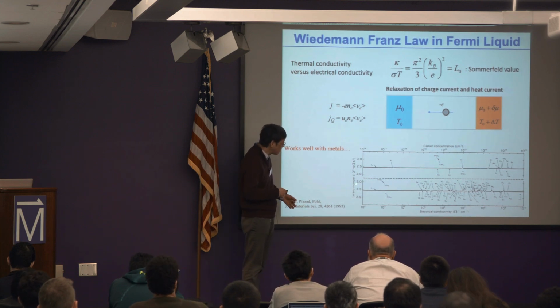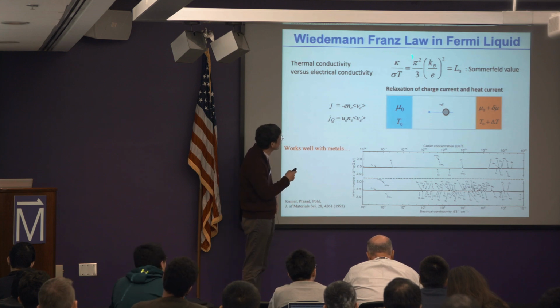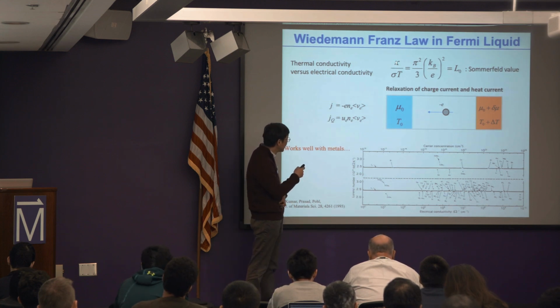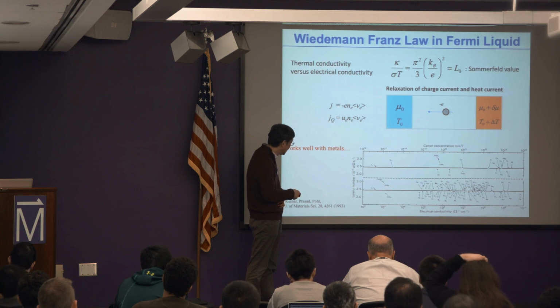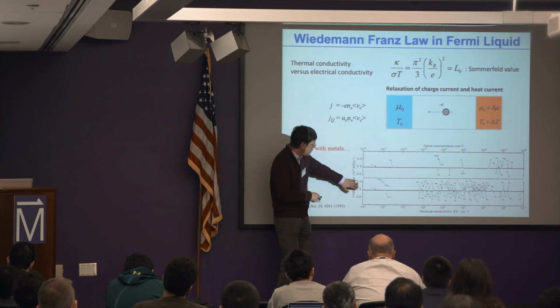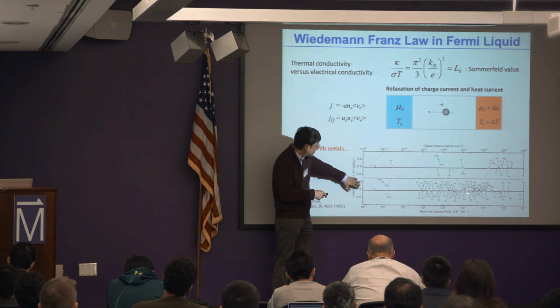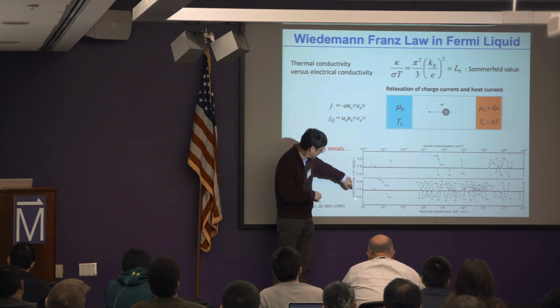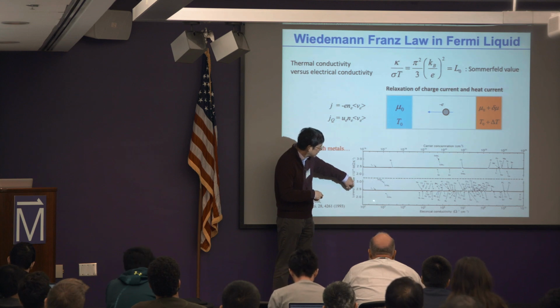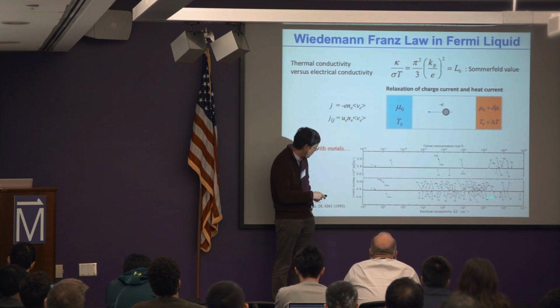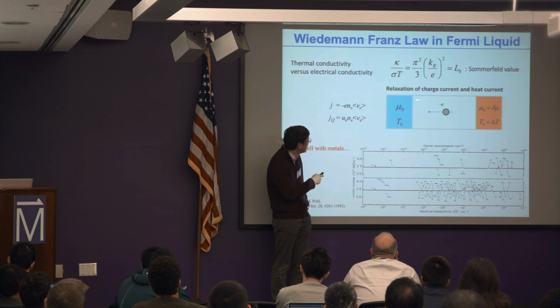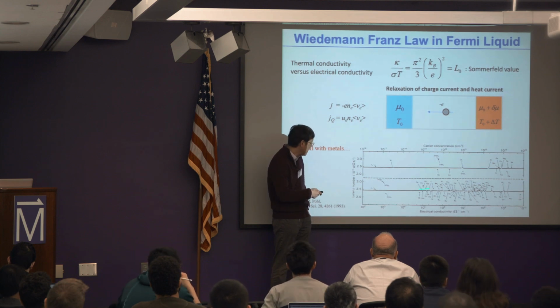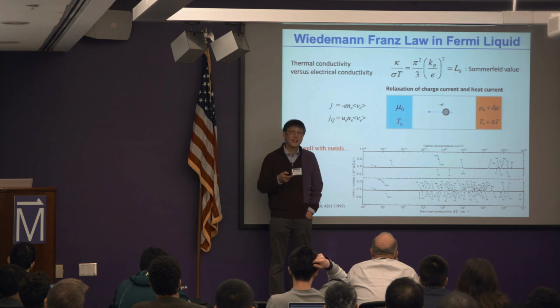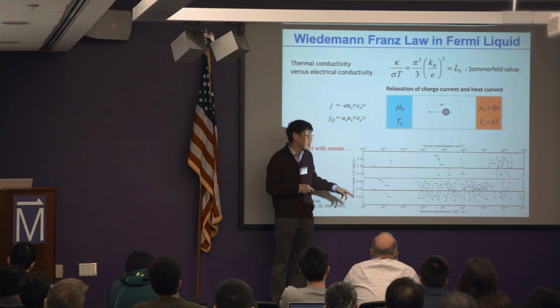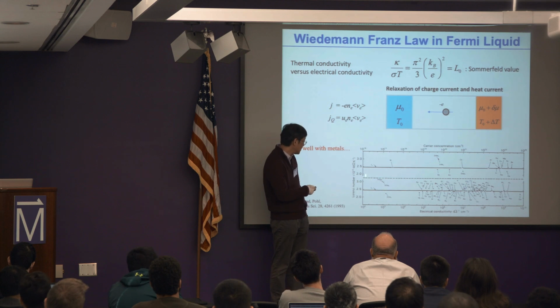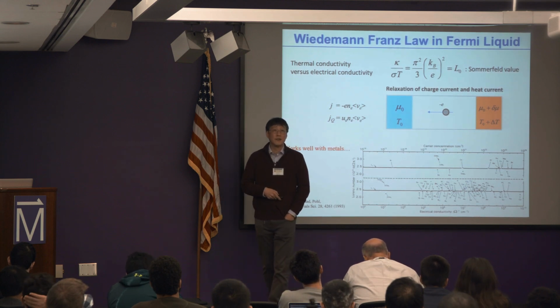And this is a table that shows the ratio of the Lorentz numbers, basically kappa over sigma T, for various different types of metals and semiconductors, right? With different electrical conductivity, and especially in the metals, they are more like 10 or 20% deviation from what is expected from the Sommerfeld value. Even for the semiconductor, as long as they're heavily doped such that it becomes a degenerate electron system, their Lorentz number deviates only 30 or 40% from what is expected.